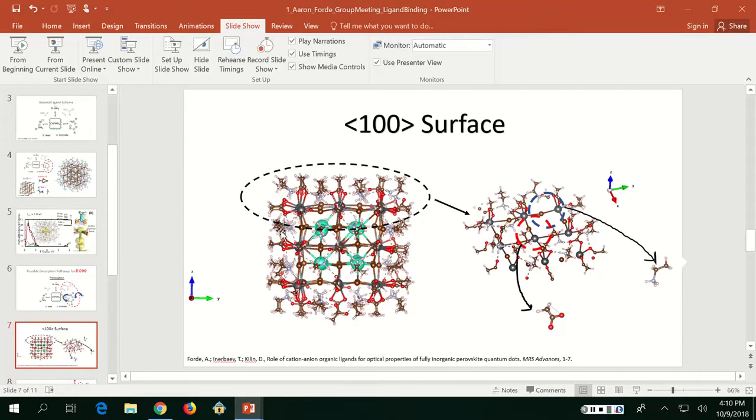So that's just my expectation anyway. At least it will be different. Yeah, it'll be different. But usually, if you see an experiment where the nanocrystals do coarsen, it's due to the 1,1,0 faces, or the corners of the crystals merging together. So that indicates that those are the weak binding spots for the nanocrystals, on the corners.